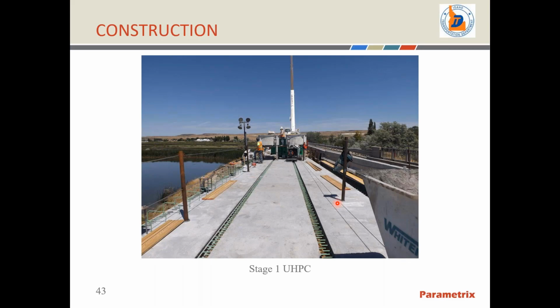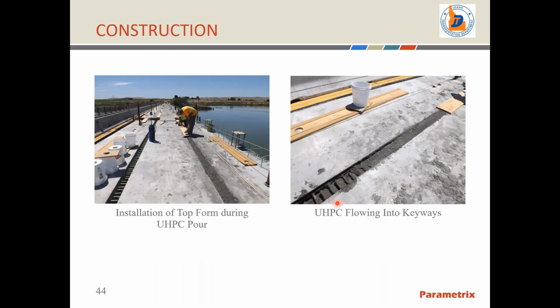Here's a picture of the equipment that was used to place the ultra high performance concrete. All batching of this material was done on site. Here's some more pictures about the UHPC placement. In order to place this material, the contractor has to form on the bottom side, but he also has to put a form on the top side because this material is so flowable with the superplasticizers and additives in it that once it starts flowing, it flows really well.